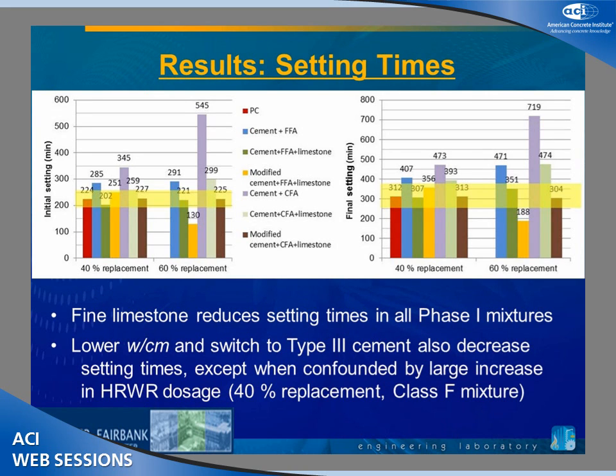So let's get into the results. For the setting time, what we see on your left is the initial setting time, and on the right is the final setting time. The control mixture is in red, so we had 224 minutes initial set, 312 for final. What we did to help you classify the data is we put a yellow band on, plus or minus 30 minutes around the control for initial, plus or minus 1 hour around the control for the final.